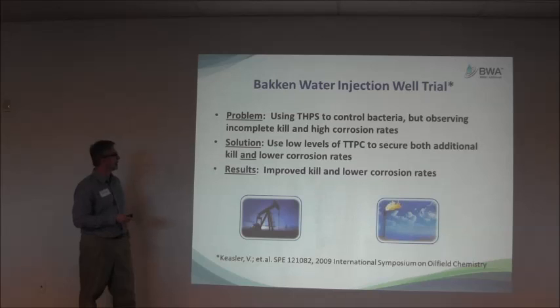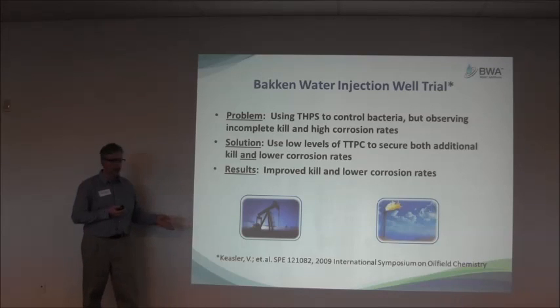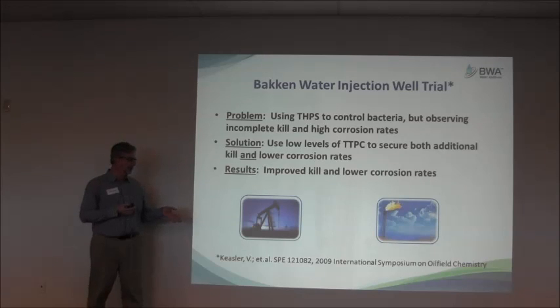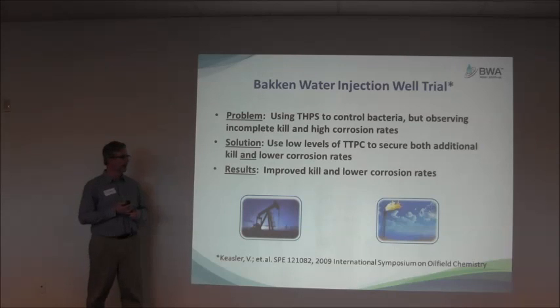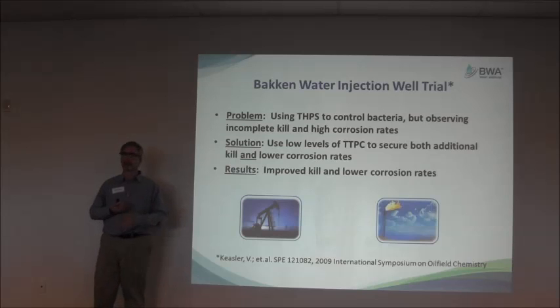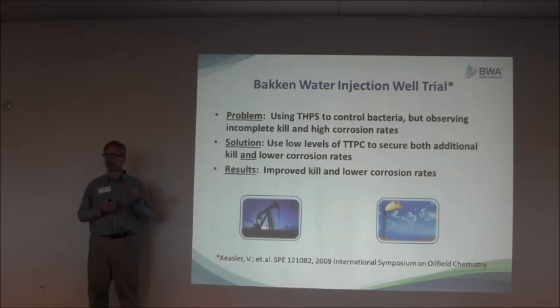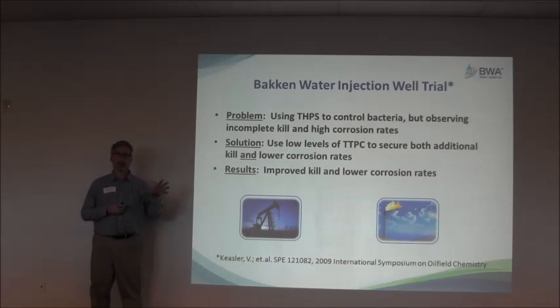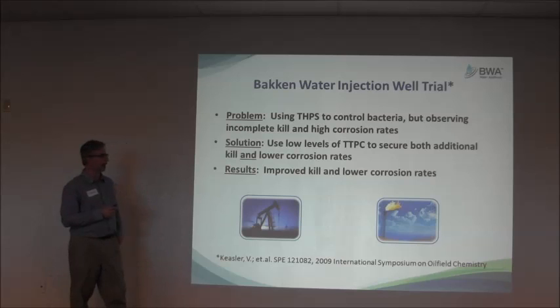This case history is from an SPE paper from 2009 — a very nice piece of work. What they did was look at an injection well in the Bakken where they were using THPS to control bacteria, but they weren't getting complete kill and were seeing very high corrosion rates. One of the issues with THPS is that it is a fairly aggressive chemistry when it comes to corrosion — you're killing the bugs but also creating some other issues with the metallurgy.